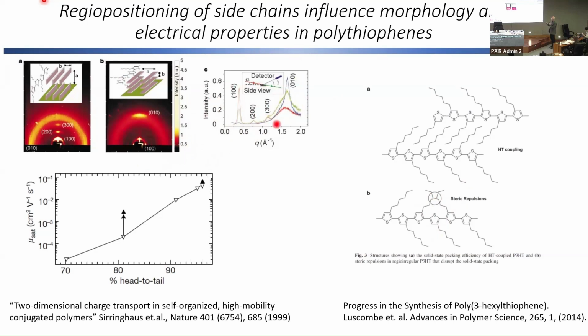And you can see this very nicely illustrated in the GIWAXS. This is grazing incidence X-ray diffraction. And when we look at a polymer that has a very high degree of regioregularity, the backbone units are stacked edge on to the substrate. Whereas if we have a lower degree of regioregularity, the polymer chains, the backbone, is now face on to the substrate. So this is a very dramatic change, right? Just by changing this side chain regularity, we could flip this orientation of our backbone from face on to edge on.